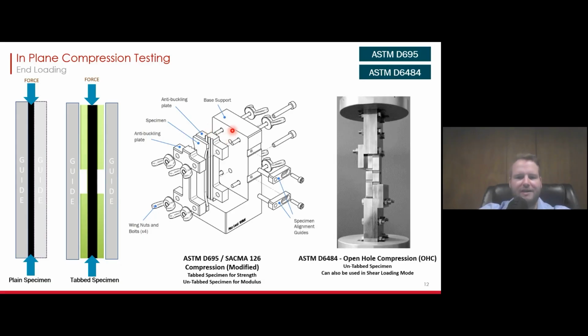And then for the ASTM D6484, that is an open hole compression test, which can be run either in end loading or in shear. So you can also use this fixture in shear, but this is the method where you're running it in end loading, where you have these end parts here. These are not compression platens. These have the shape where the fixture fits into, and then you still put that in between compression platens, and you can load your open hole specimen in compression that way with end loading.